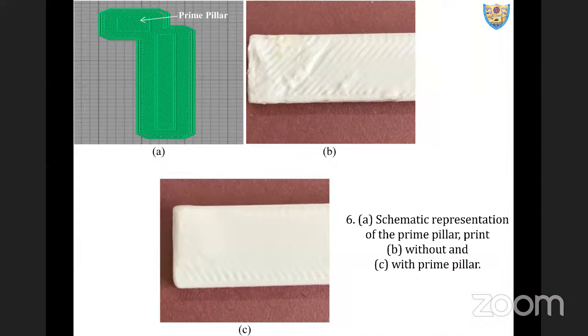Now this, especially when we're talking about printing of sandwich structures using a single nozzle system, is a difficult task, in the sense, I'm not saying it is not possible. Using the same nozzle, you can print a sandwich as well, but you need to keep on changing the filament. And in case of a multi-nozzle system, there is every chance that the second nozzle might not start precisely at the same location from where you need to start. So we print additionally, and then we cut it off, and that is known as a prime pillar. This is without prime pillar, wherein the deposition gets improperly laid. But with the prime pillar, as defects are localized to an additional part which can be cut later, we can get a good sample. So this is one more facet we can look into.